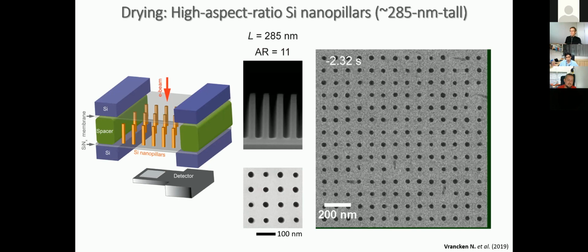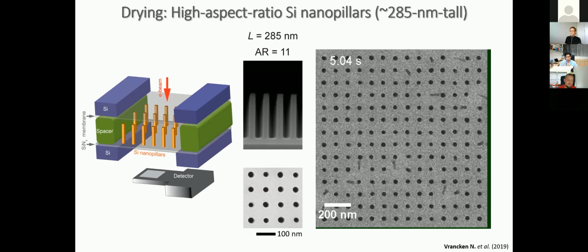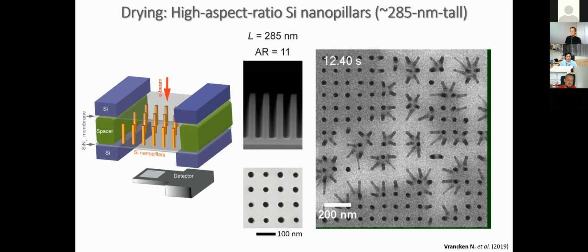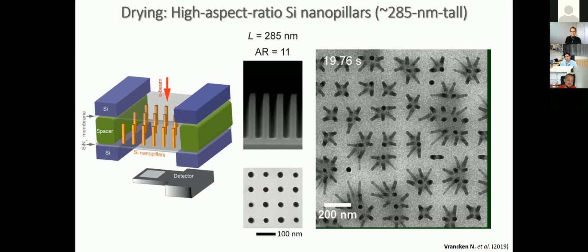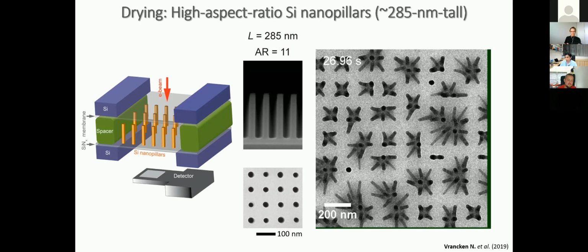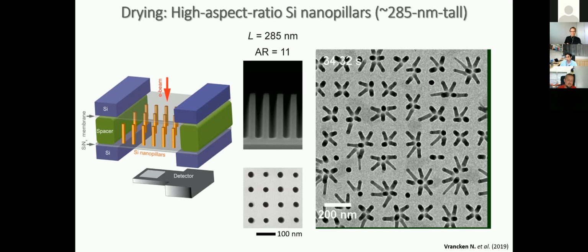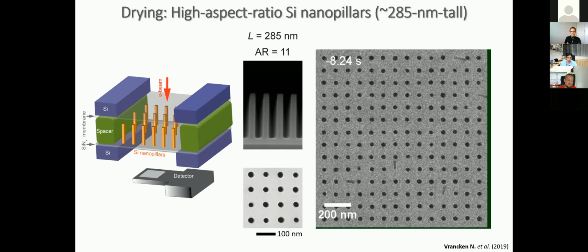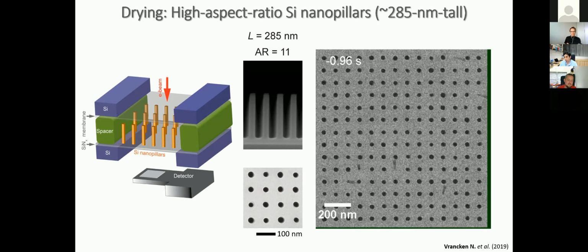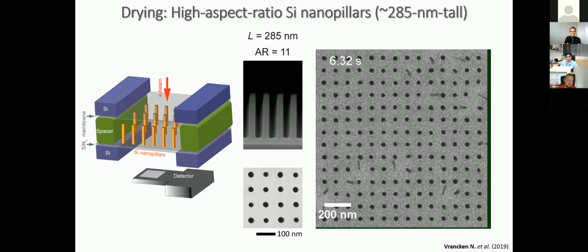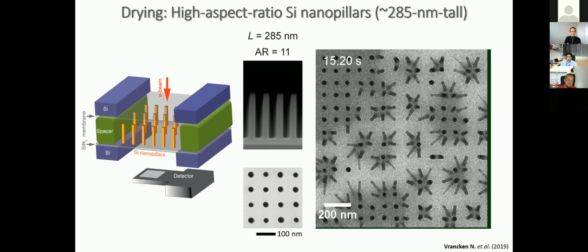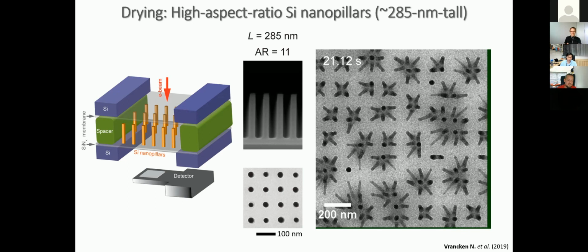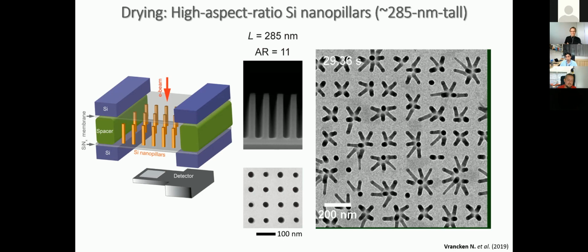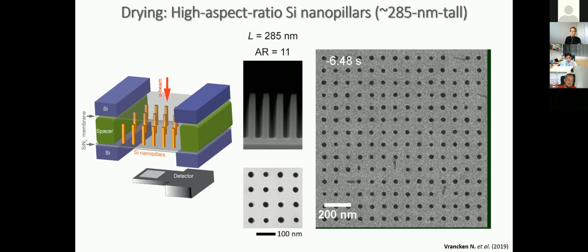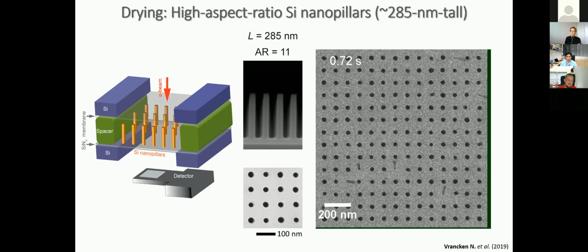So water leaves, you have this trace amount of nano droplets that bind them together, and then once this leaves, because of the adhesion between these nanostructures, you're permanently damaged. So you're done. Game over, right? Almost everything is damaged. If you want to build the transistors, over, I don't know, 1,000, maybe one survived. Not good, right? When the industry says even 99.9 is not good for them, their tolerances are much higher. If you do an experiment and you have a 10% or a 50-60% success rate, it's good. But for industry, you build 1 billion transistors, they want almost all of them functional.